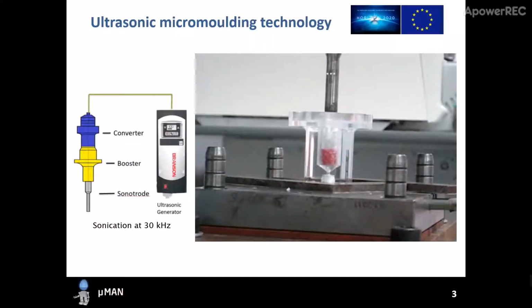This is actually the heart of the ultrasonic micromoulding technology. Basically we have an ultrasonic stack, which you can see here. It is made of a converter, a booster and a sonotrode, and also an ultrasonic generator on the right hand side. This one generates electrical signals, and these are connected to this converter. This device converts the electrical signals into mechanical displacement using the piezoelectric effect, and these ultra-fast vibrations are amplified using this booster here. And with this sonotrode we make contact with our polymer pellets, and the energy transfer is carried out using this sonotrode and the pellets, and this vibrates at 30 kilohertz, and it's quite fast and energetic.